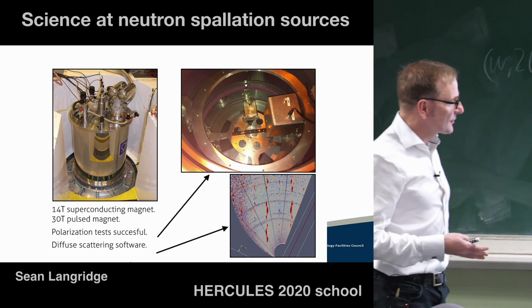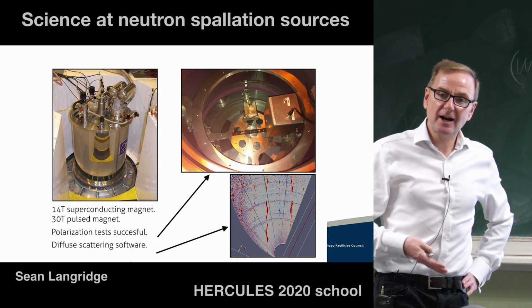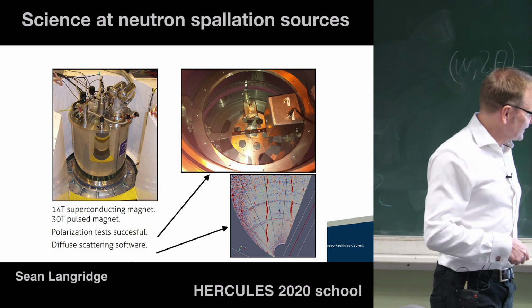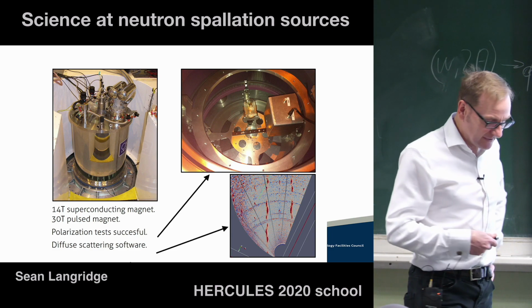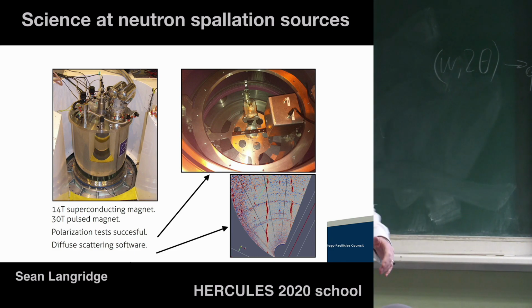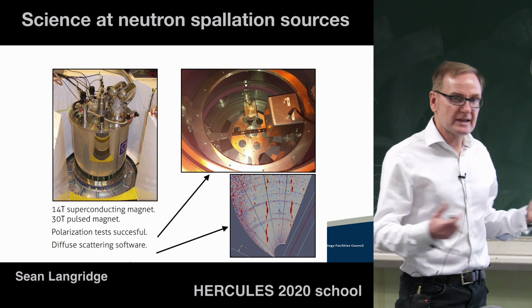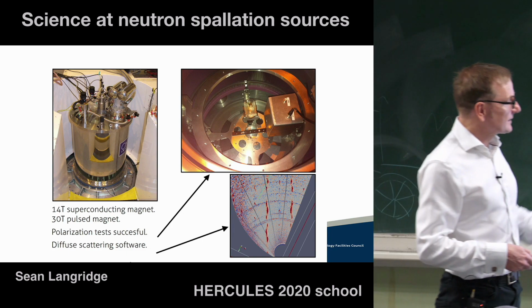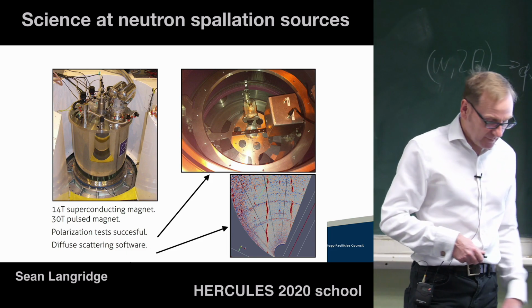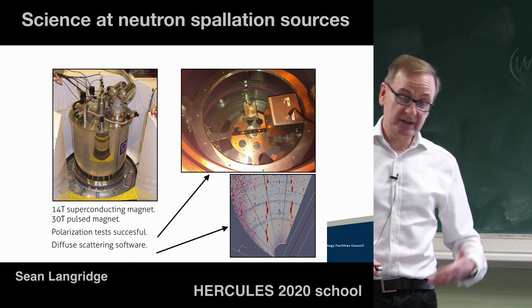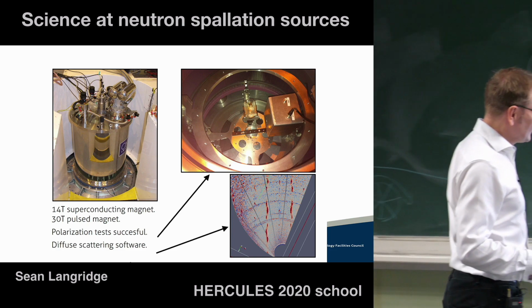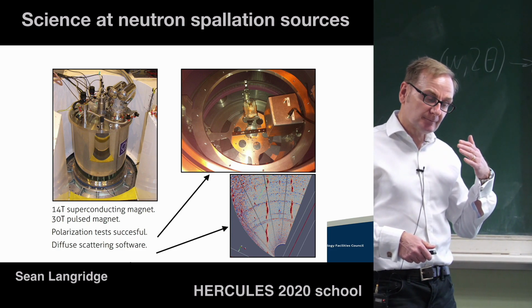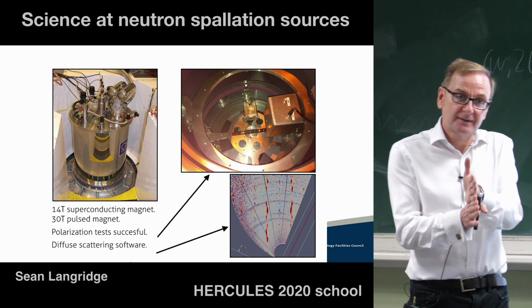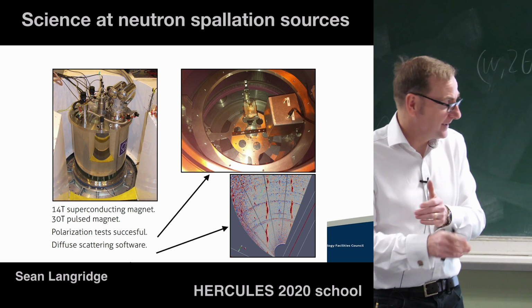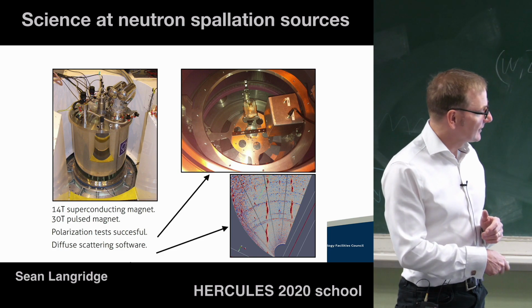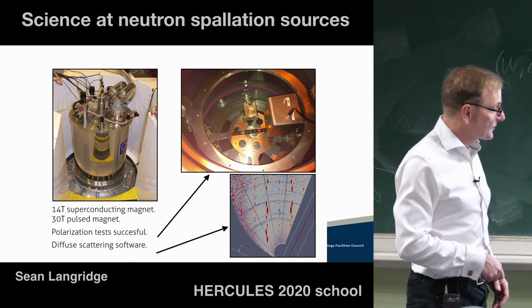It also means, because it's the pulse source, that you can use things like pulse sample environment. Okay? So in this case, a conventional magnet on a conventional source, there are higher examples, but 14 Tesla is not a bad field for a superconducting magnet in steady state. On a pulse source, you can use pulse magnets. So you can do 30, 40 Tesla and pulse the magnet to coincide with the pulse of the synchrotron on our spallation source. Okay? So that means you can do measurements in much higher fields than you can do, again, because it's a pulse source.